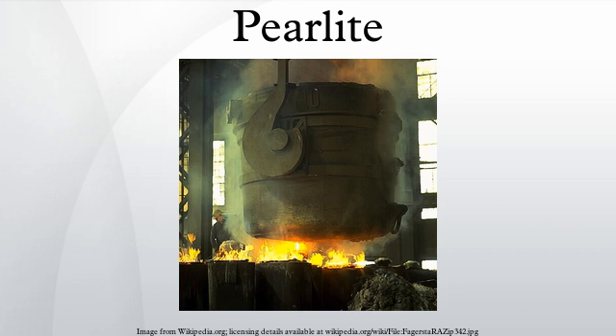Although pearlite is used in many engineering applications, the origin of its extreme strength is not well understood. It has been recently shown that cold wire drawing not only strengthens pearlite by refining the lamellar structure, but also simultaneously causes partial chemical decomposition of cementite, associated with an increased carbon content of the ferrite phase, and even a structural transition from crystalline to amorphous cementite.